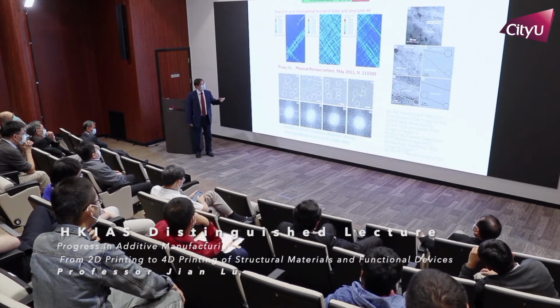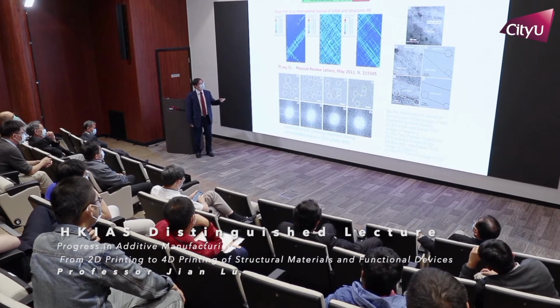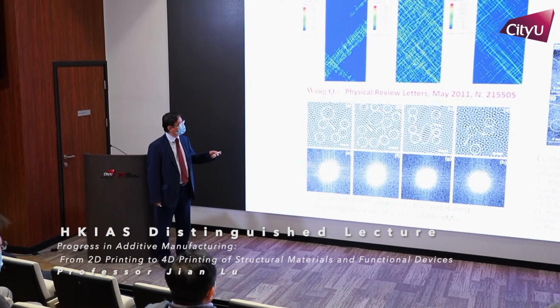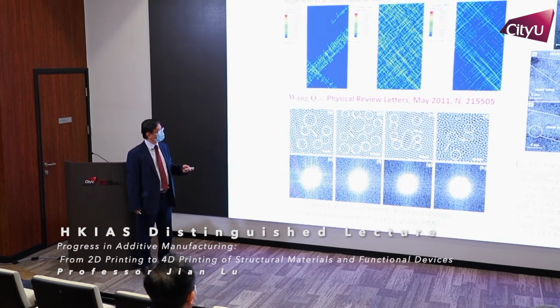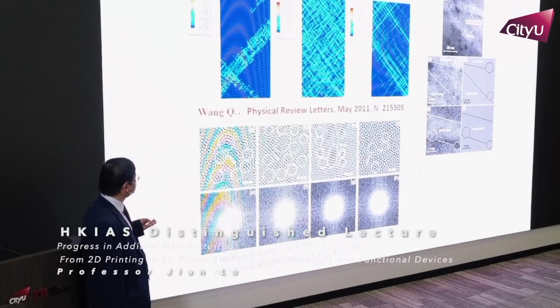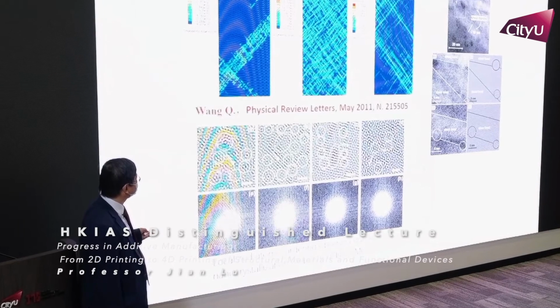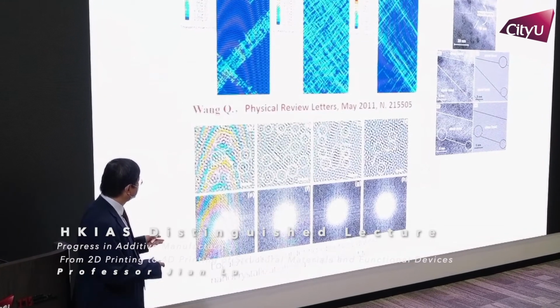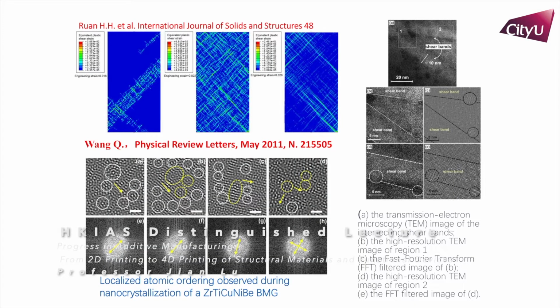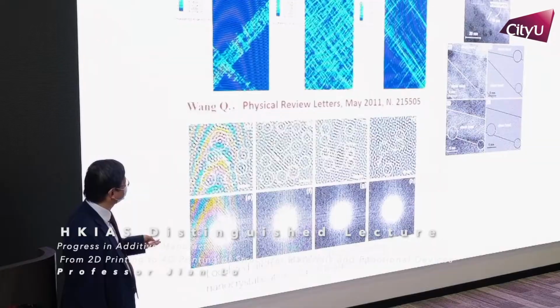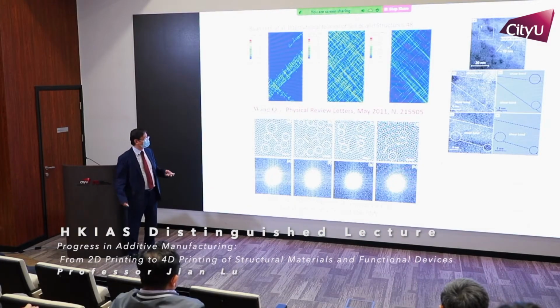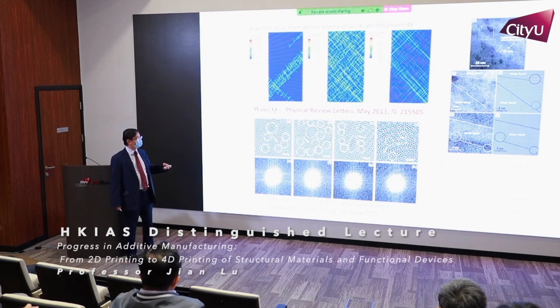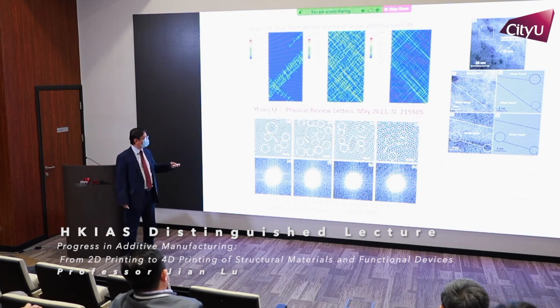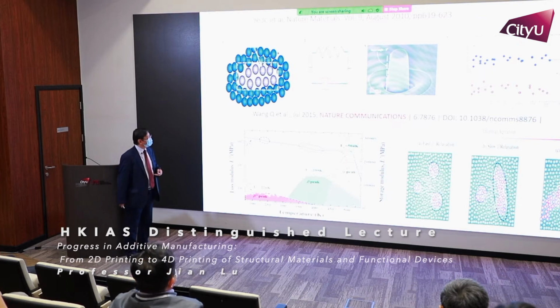But if we are able to generate a structure that naturally generates a multi-shear band structure, then we can solve the problem. Then we tried to use the heat treatment to generate a material mixed with glass and nanocrystal, but it's very difficult because thermal heat treatment is not easy to manage at the atomic level. So for this reason, we only observe some change and some mixture, but it's very difficult to put it, say, homogeneously across a volume.